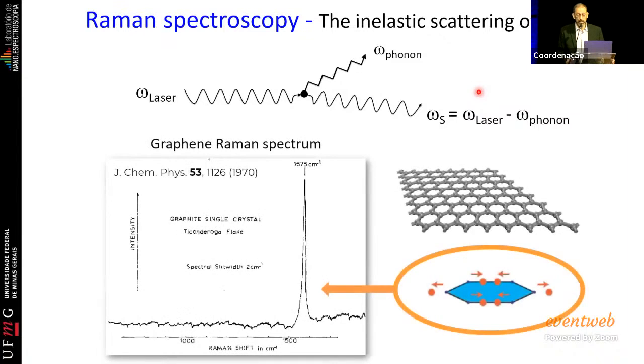And if we look into graphite or graphene, what we have is one very strong peak at a Raman shift, which is usually measured in wave numbers, okay? And what you are seeing here is basically this displacement of the scattered photon with respect to the incoming photon due to the generation of one quantum of atomic vibration that is represented by these movements here. So this would be the graphene at equilibrium, but then you have the stretching of the carbon-carbon bonds. This stretching has a given frequency. This frequency is dictated by the mass of the carbon and by the strength of the chemical bonds. So this vibration brings you information, indirectly, about the thermal properties, the mechanical properties, the electronic properties, etc.